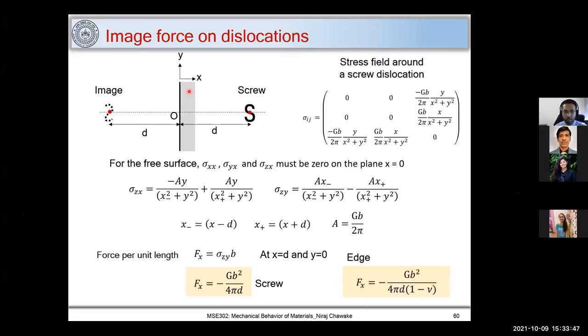Now, I am coming to an end of my talk. So this is an important point, which most of the time we don't consider, that is the image force on dislocations. So let's consider this is a surface, and here your dislocation is lying. I mentioned a screw here. This surface will exert some force on this dislocation, and when it does, this dislocation can move towards the surface and get removed from the material, and thus you lose information.